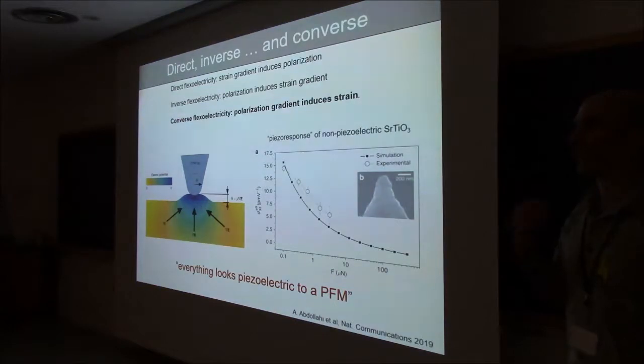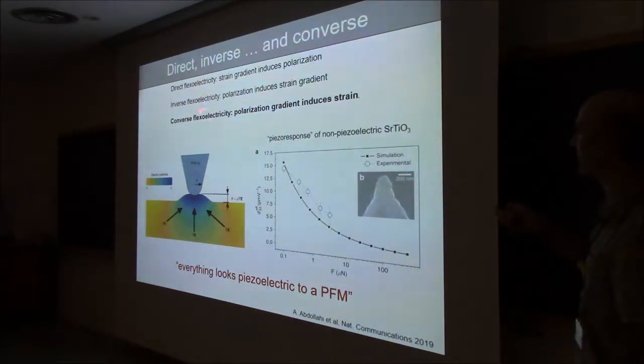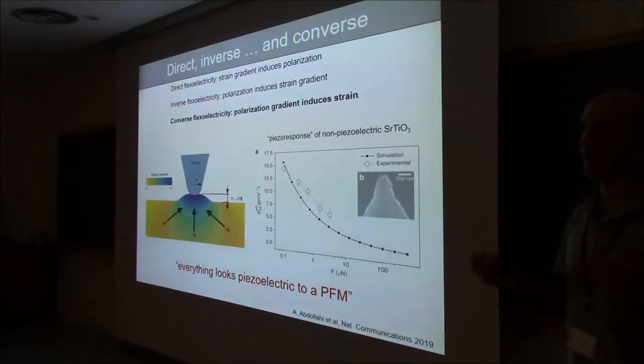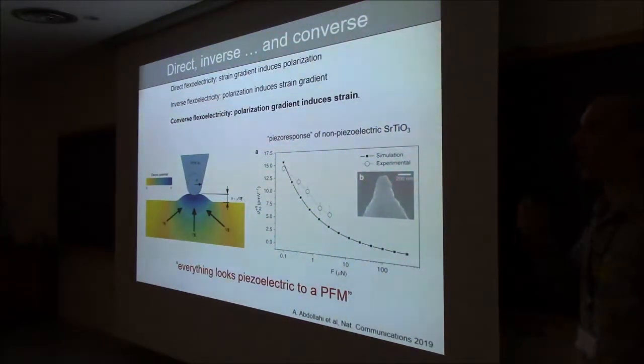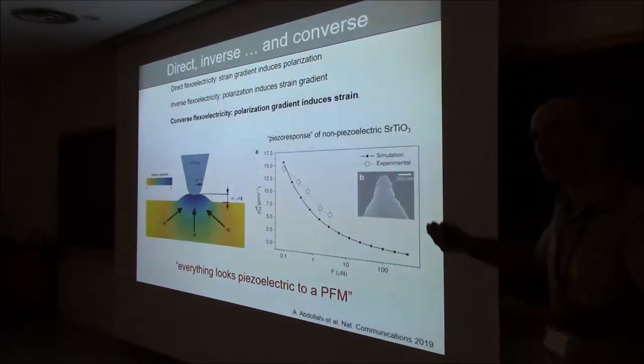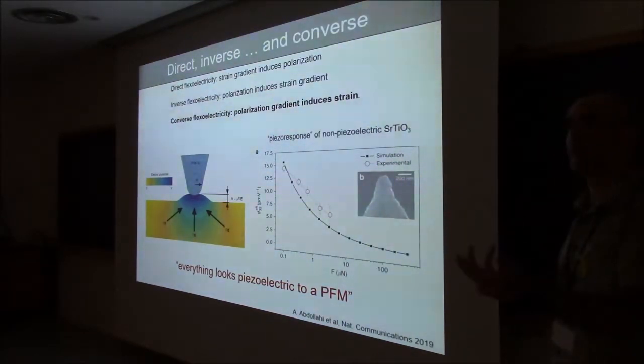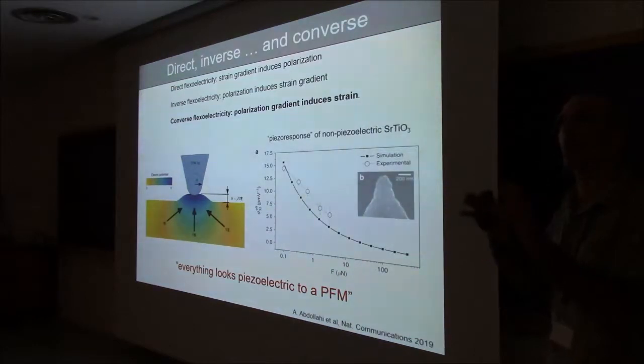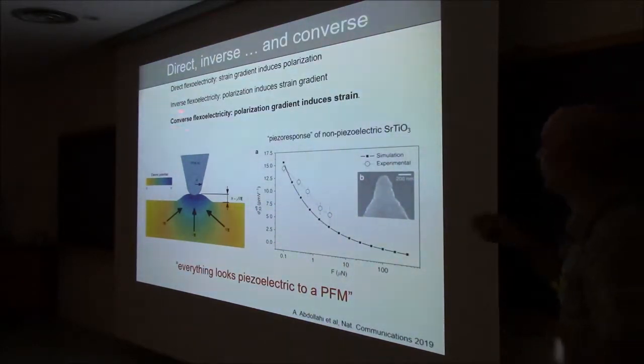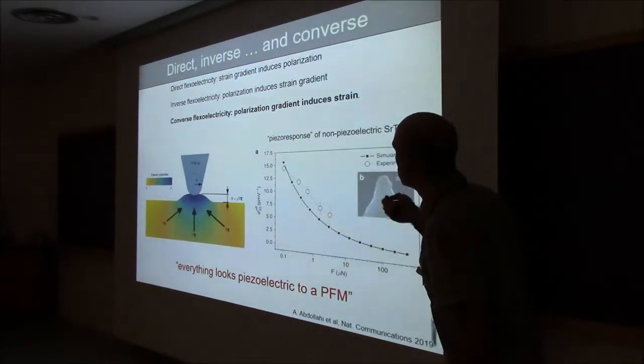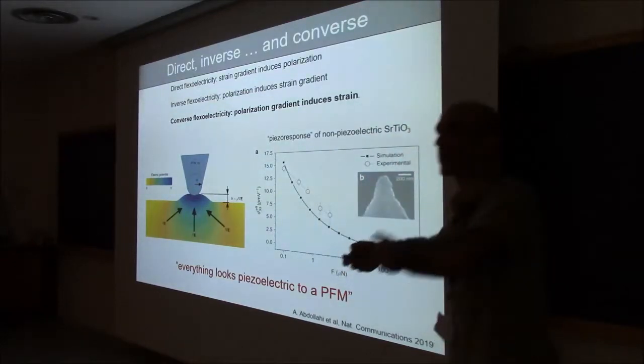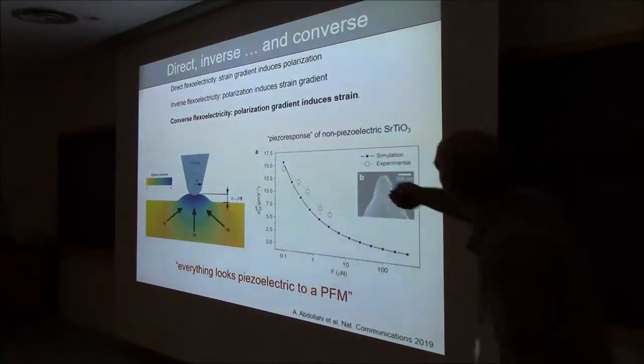It can be proven, but I can't because I'm not smart enough, that in fact inverse flexoelectricity and converse flexoelectricity are two manifestations of exactly the same thing. But even though they are essentially the same thing, experimentally they have quite different consequences. So if you want to measure inverse flexoelectricity, as you say, you apply a voltage and that will induce a strain gradient, something will bend. Okay.